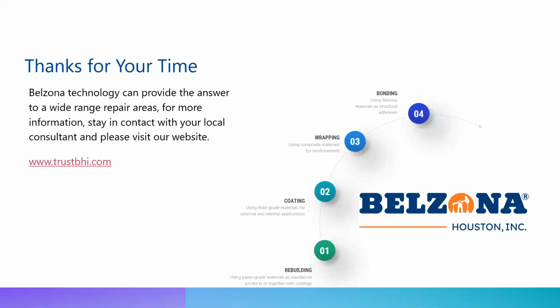I would coat it if it's in the UV. It'll turn a little yellow and it shouldn't affect the mechanical properties too badly. But it's easily top coated the next day with any sort of UV product. You can just put it on top and protect it. It is highly chemical resistant, so it can handle chemical spillage on it, or chemical contact from the inside. But if it's going to get direct sunlight, I would give it a UV top coat.